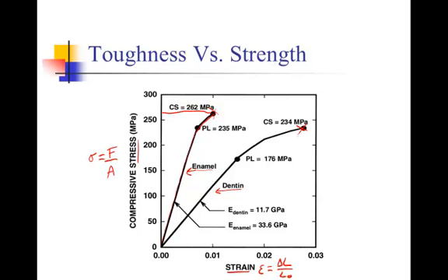However, the toughness is related to the area underneath this curve. So if we drop a line down here and shade all the area under the curve, and do that for tooth enamel too, you will probably be able to estimate that tooth enamel has less area under its fracture curve than dentin does. And so dentin would be the tougher material, which can absorb more total energy before it fails. But tooth enamel is the stronger material, actually going to a higher stress before it fails.